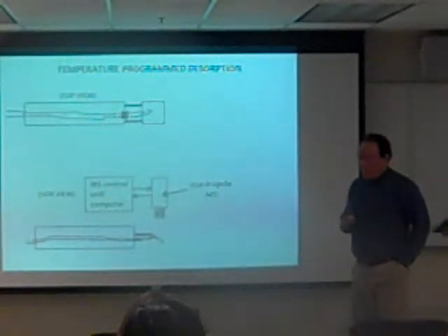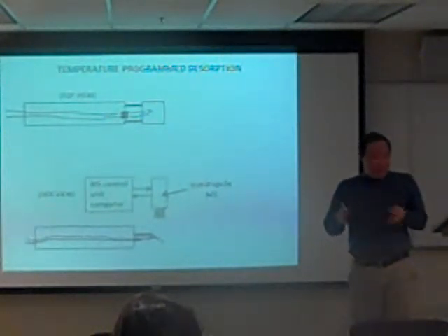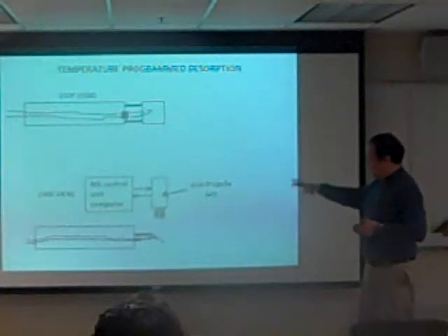And one question that you might ask is, wait a minute, you're doing these experiments in ultra-high vacuum. Aren't you interrupting equilibrium conditions? Well, it turns out that it's okay. Basically, we're able to get complementary kinetic data. And to explain this data, I have to explain this technique here. It's called temperature programmed desorption.